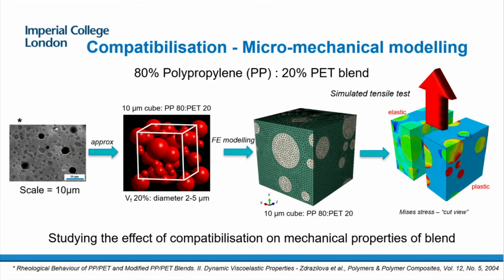So this is a literature picture. Based on this image, you can make a virtual material, with the same size distribution and volume fraction as the original. And then you can do virtual mechanical tests to understand what the mechanical properties of this material are as a function of the adhesion between the two polymers. We're in the process of actually doing our own experiments, as well as using the literature experiments, in collaboration with the aero department.